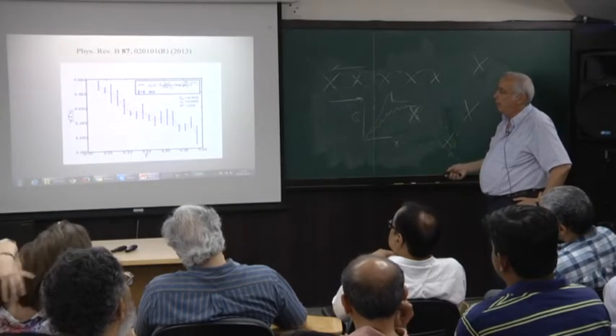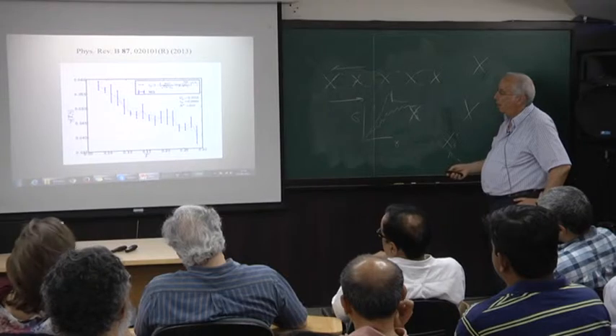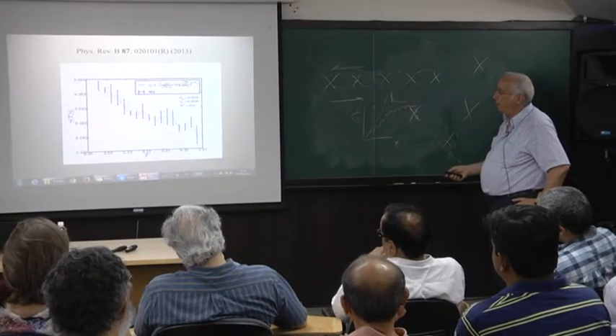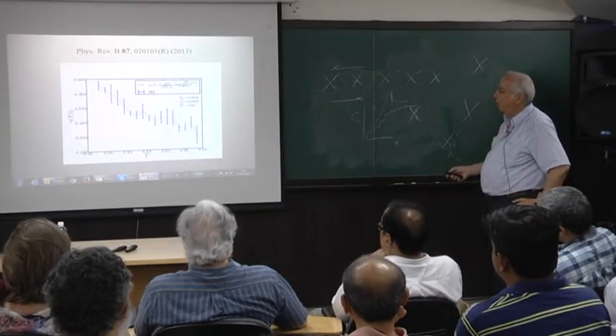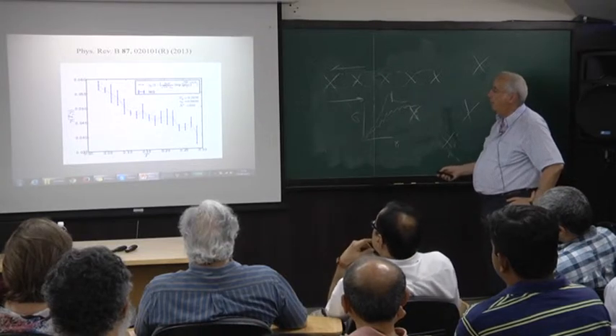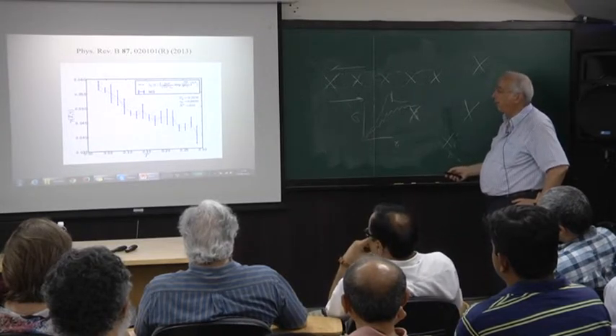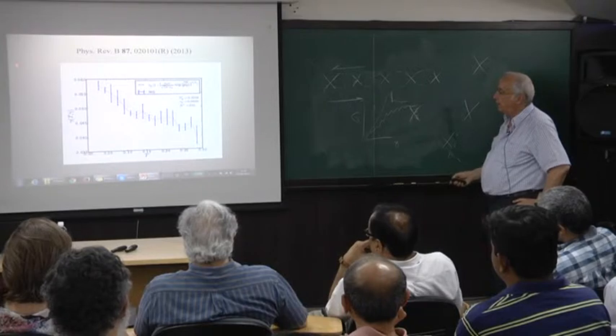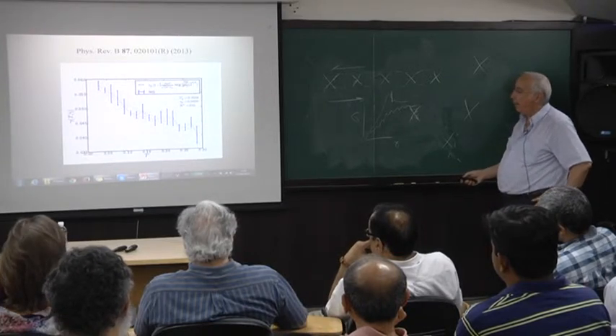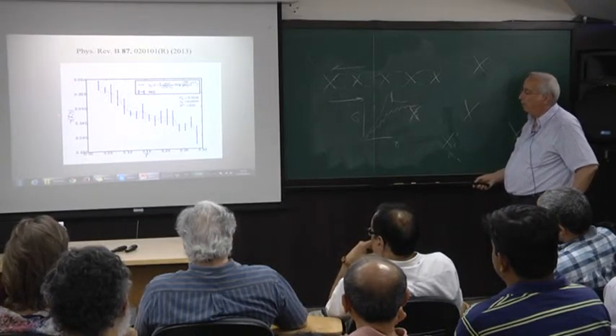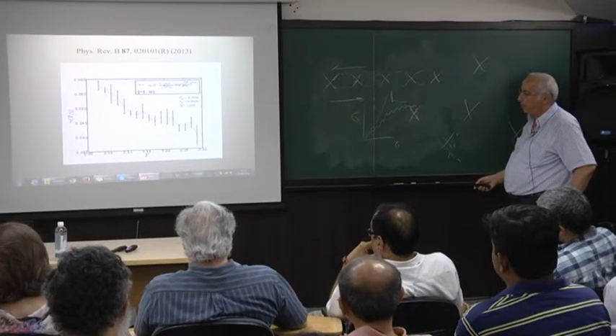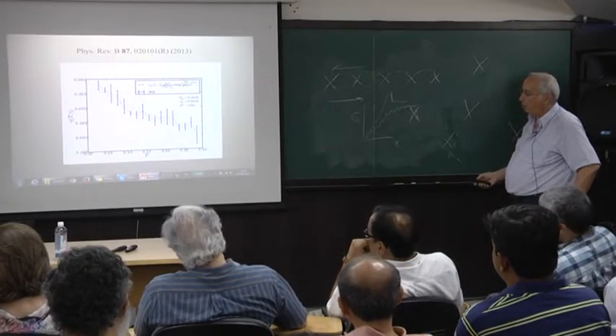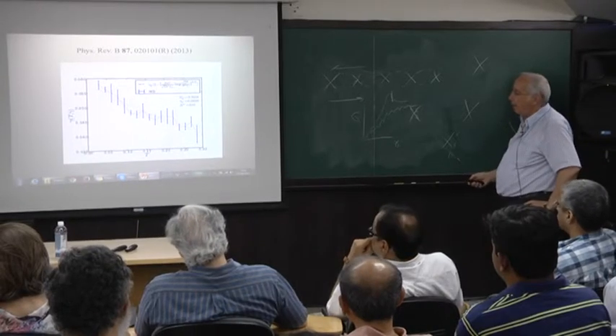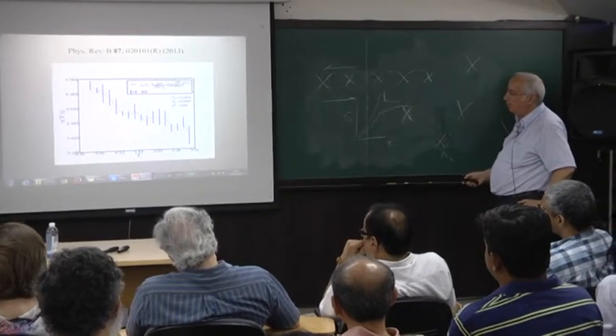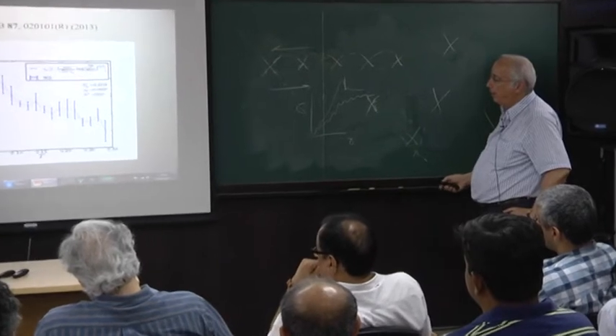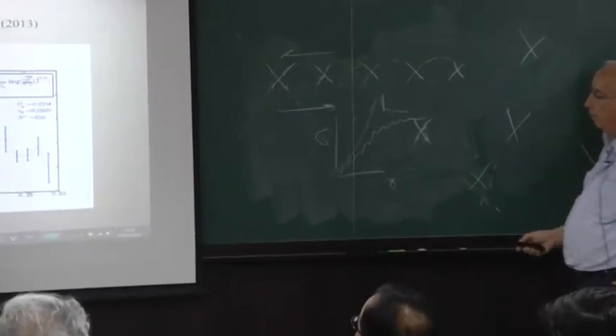And when you do this, you get a law that is exactly the law of Johnson and Samwer, except that now we know all the coefficients. So this is a comparison with the numerical simulations at different temperature and gamma dot. This was done by Ashwin J. And in fact, there's no free parameter here. Everything here is computable from the theory.